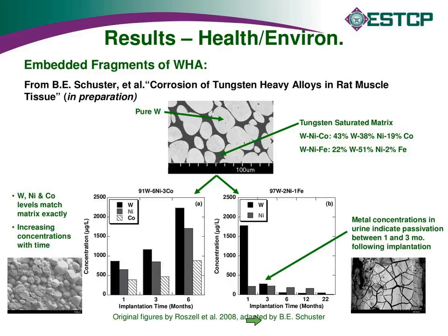You have this two-phase microstructure where you have pure tungsten particles that are surrounded by a matrix phase, and for the tungsten nickel cobalt alloy, the composition of this matrix phase is 43% by weight of tungsten, 38% by weight of nickel, and 19% by weight of cobalt. For the tungsten nickel iron, it's more like 22% by weight of tungsten, 51 nickel, and maybe 2% iron. And if you look at the concentrations of metals present in the urine of the rats taken at different time points, so 1, 3, and 6 months, you see an ever-increasing concentration of tungsten, nickel, and cobalt. And if you normalize that ratio, it matches that matrix exactly.